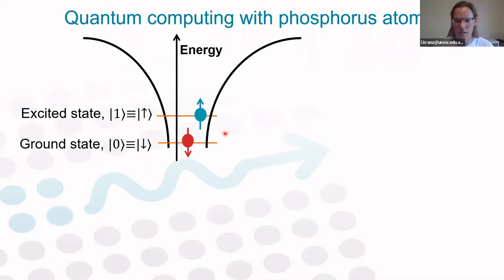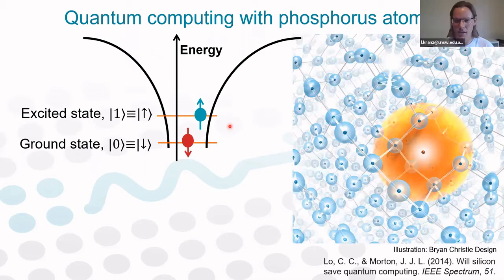And in practice, we achieve this confinement potential using phosphorus atoms in silicon, which is shown on the right here in the schematic, where the red dot represents a phosphorus atom within the silicon crystal lattice, where the phosphorus atom replaced one of the silicon atoms. And the orange sphere corresponds to the electron wave function. And it's important to note that the phosphorus atom is a donor, so it donates this electron to the system. And we perform experiments at cryogenic temperatures, where this electron doesn't have enough thermal energy to go into the conduction band, and instead it will freeze at this site of the donor.